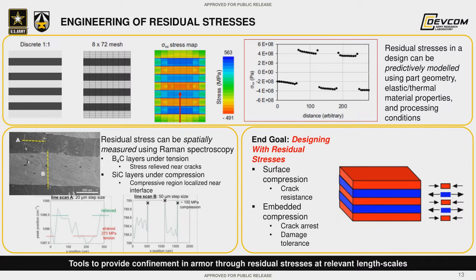So our end goal here is to give us the ability to design with residual stresses, so we can do things like introduce surface compression and crack resistance, as well as embedded compressive resistance to control how failure occurs in these materials during high impact events, and in order to give us improved performance that we're not able to realize through conventional processing.